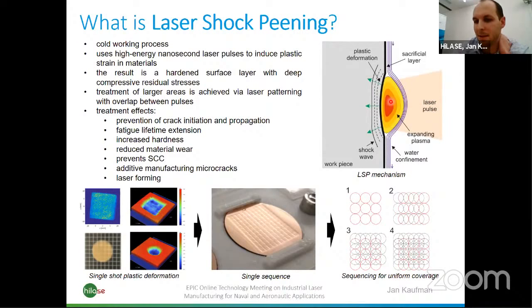And the plasma is basically overheated gas, which expands very rapidly, sending a high pressure shock wave inside the material and causing plastic deformation. I'd like to stress here that it is a cold working process, which means that no heat gets transferred from the explosion over here to the workpiece over here, thanks to the sacrificial layer that absorbs all the heat effects, and what is left is only the pressure that causes the plastic deformation. The result you can see over here.